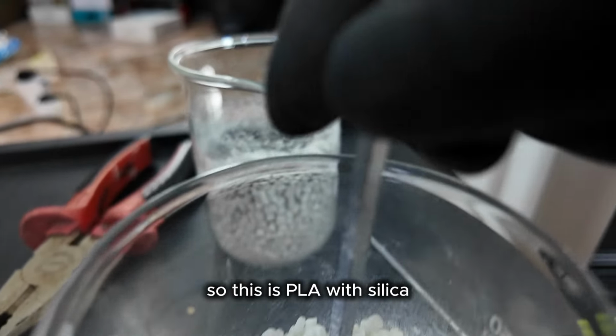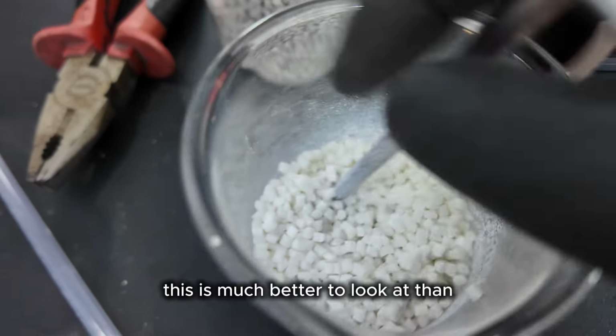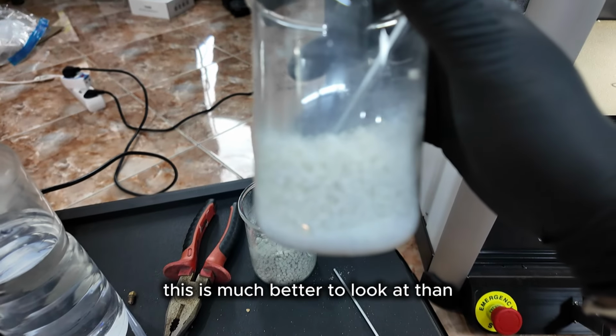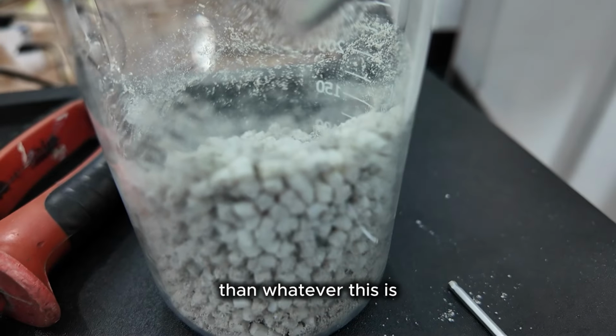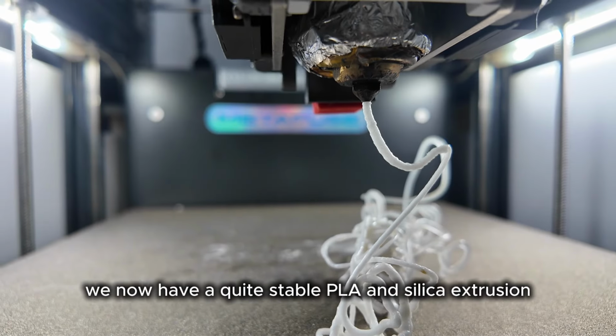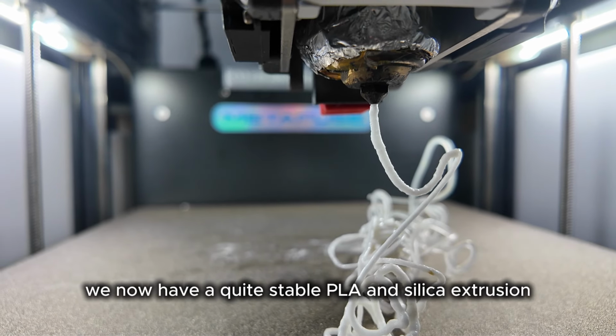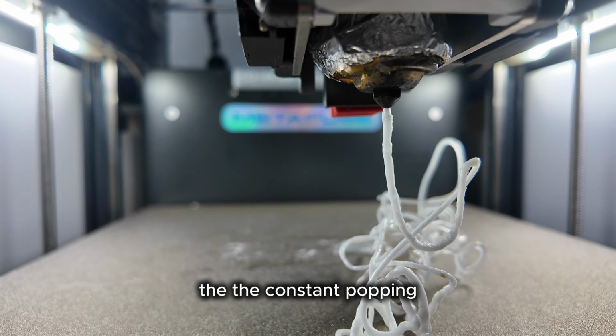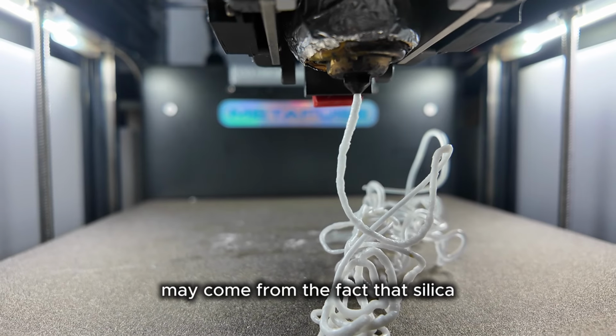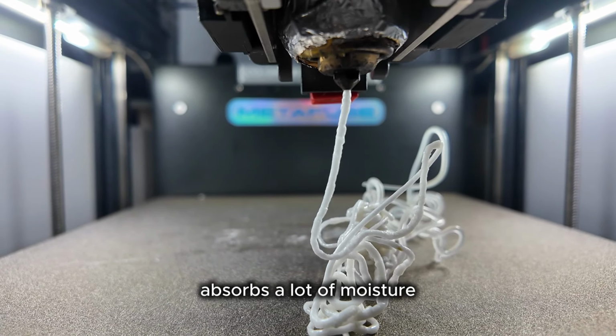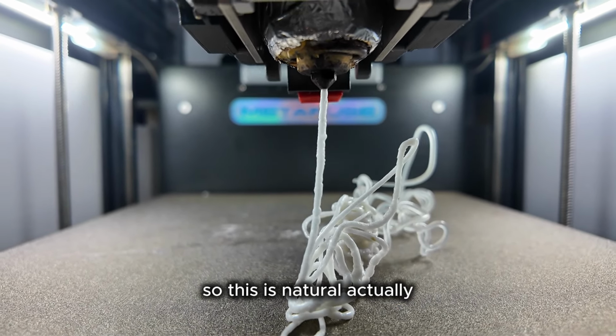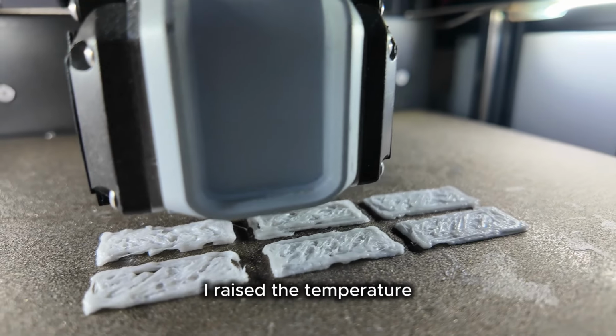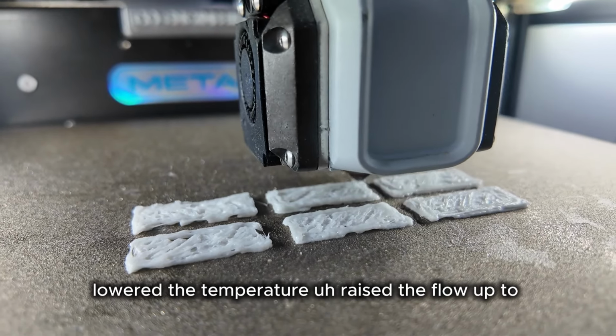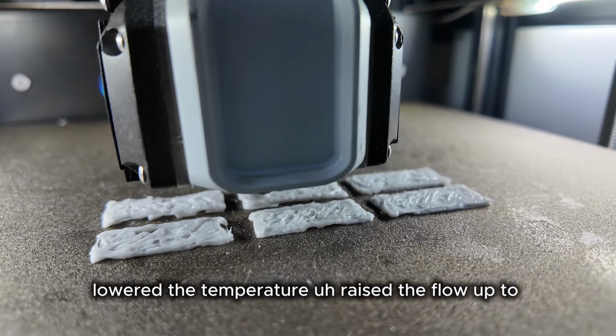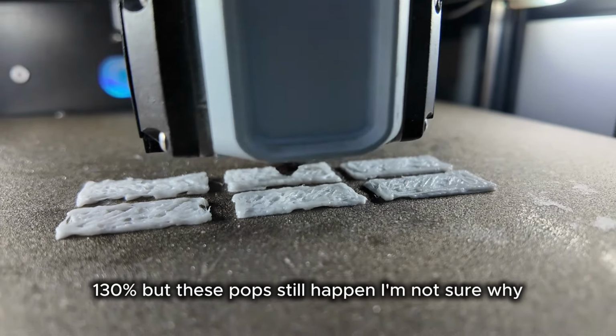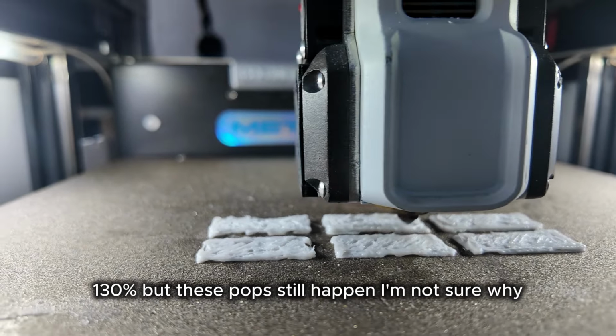So this is PLA with silica. This is much better to look at than whatever this is. We now have a quite stable PLA and silica extrusion. The constant popping may come from the fact that silica absorbs a lot of moisture, so this is natural actually. I raised the temperature, lowered the temperature, raised the flow up to 130%, but these pops still happen. I'm not sure why.